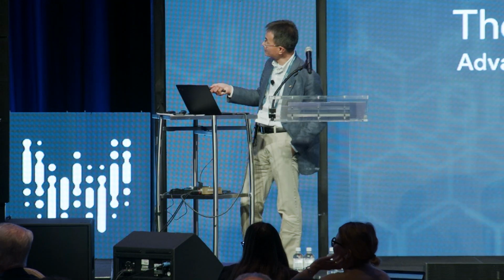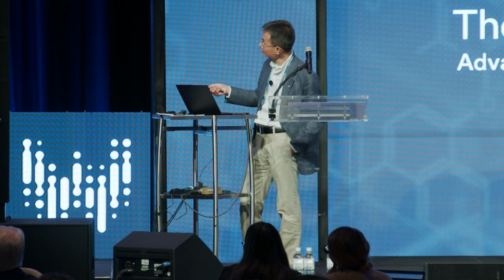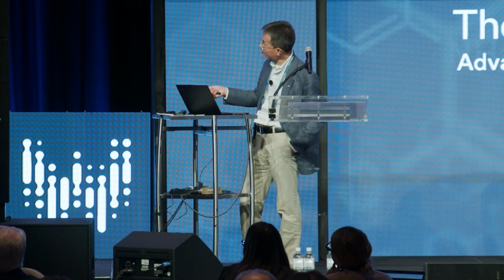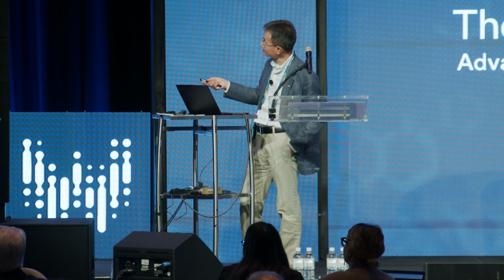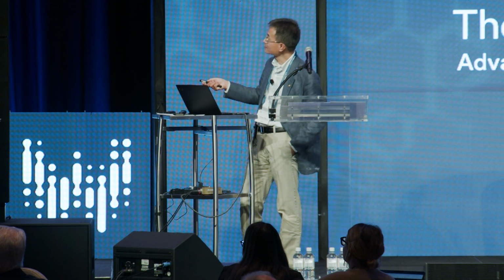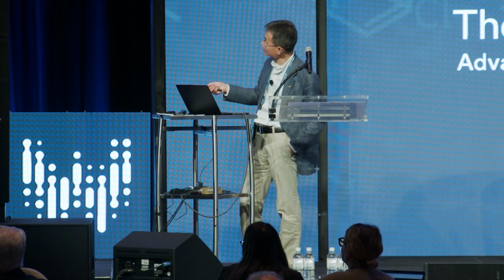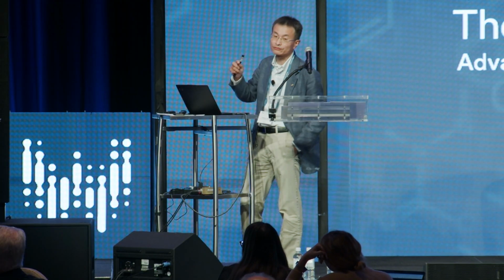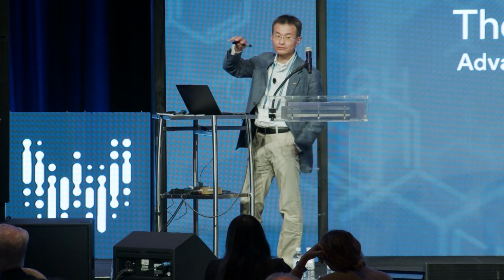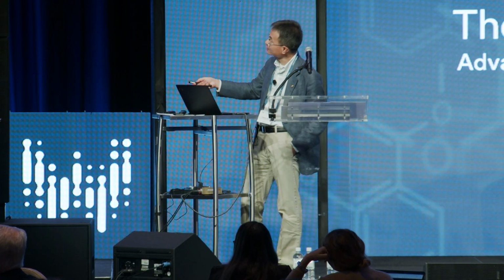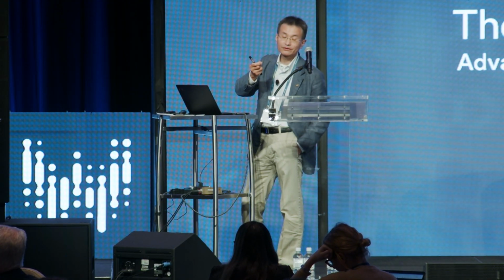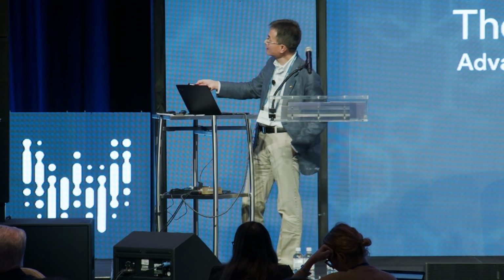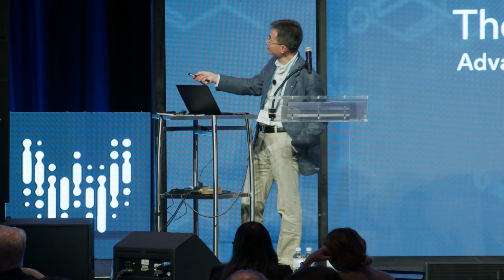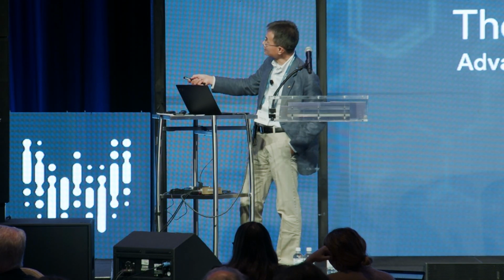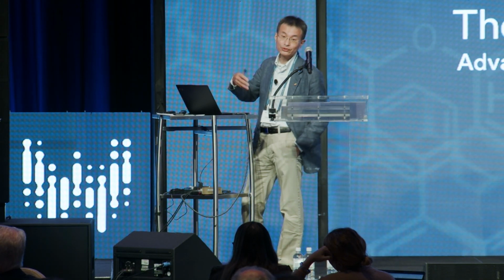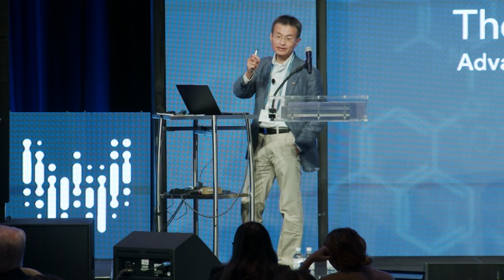So what happens is that optically excited nanowires provide electrons to these microorganisms. Within these microorganisms, we have the acetyl-CoA pathway. In this particular example, the electron generated from the semiconductor serves as a reducing equivalent that propagates into this biological system as other reducing equivalents like reduced ferredoxin, NADH, NADPH. They enter into this acetyl-CoA pathway and eventually fix CO2 into, in this case, acetate with almost unity selectivity, yet with an overpotential of only 200 millivolts.